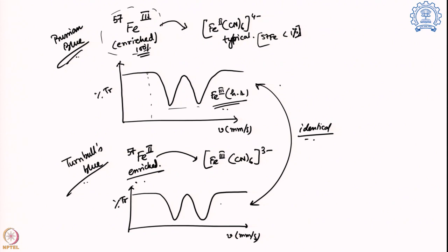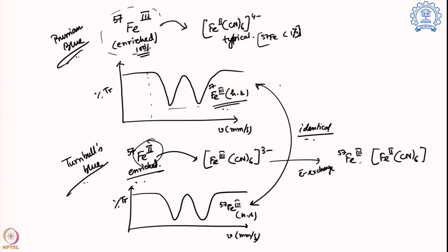Because over here I am again seeing the iron 57, nothing else. And this signature is for iron 3 high spin, but when I add it, it is iron 2. But during the reaction, it actually exchanged the electron and becomes iron 3 on the outside, and the complex ion becomes iron 2, and they created the complex they require. And over here, because of this electron exchange happening, I am getting iron 57 as a result.